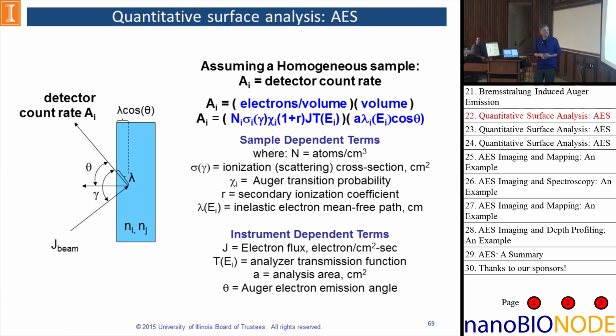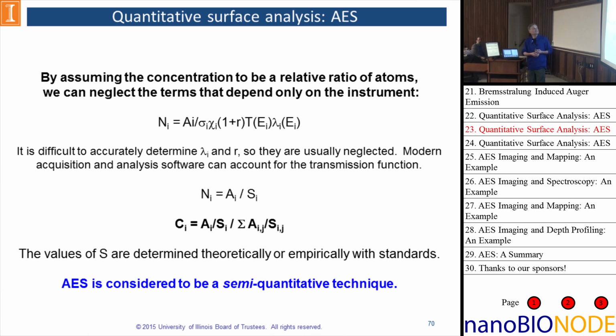But like I said earlier, because we calculate the percentages as a concentration, we can remove the instrument-dependent terms, lump all the rest of these terms into a relative sensitivity factor, and then use that for quantification. Now, Auger, because of its difficulties of overlap with other peaks, it's not quite as quantitative as XPS. It's going to be more on the semi-quantitative side.